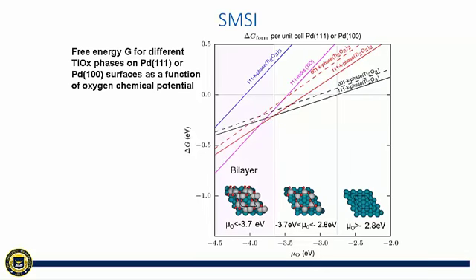We can see there is an intersection between the two curves at an oxygen chemical potential equal to minus 3.7 eV. So this indicates when the oxygen chemical potential is below minus 3.7 eV, the crystalline bilayer is the most stable phase. We can see another intersection of the solid black line with 0. So between minus 3.7 eV and minus 2.8 eV, the crystalline monolayer is the most stable phase. If the oxygen chemical potential is higher than minus 2.8 eV, the null layer will form on the surface of the metal particle.